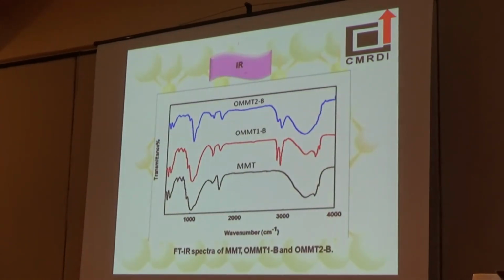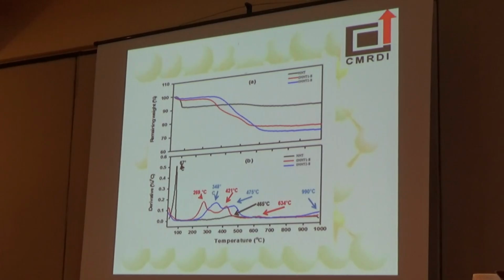Infrared spectroscopy shows that for the modified clay samples, 2 new peaks appeared in the 2 modified clay samples. These 2 peaks were ascribed to the CH asymmetric and symmetric stretching vibration of the long alkyl chain present in the 2 surfactants.